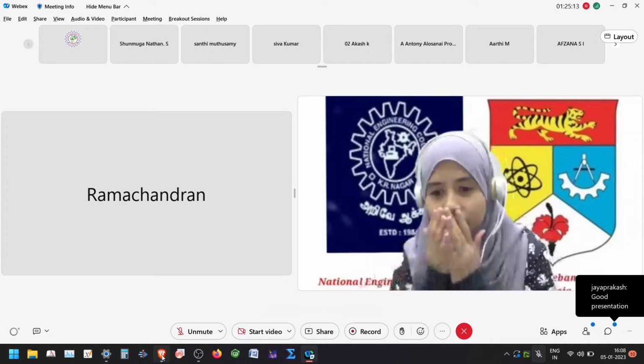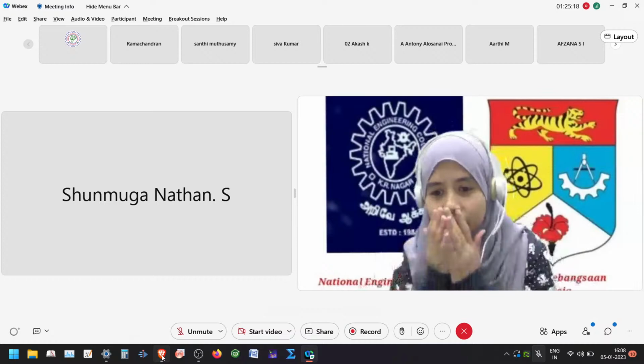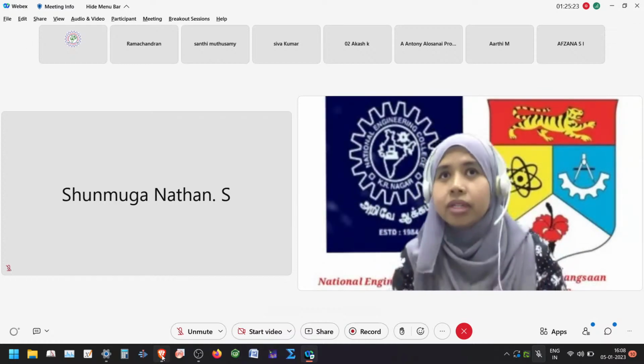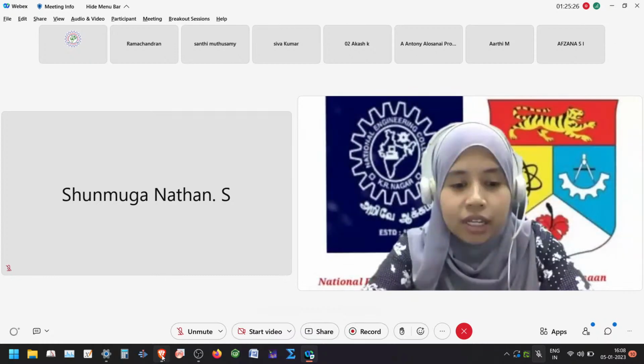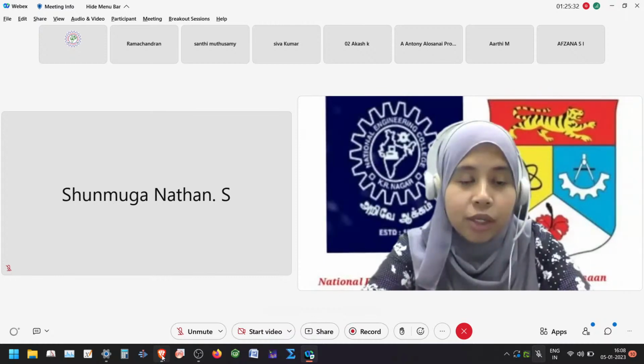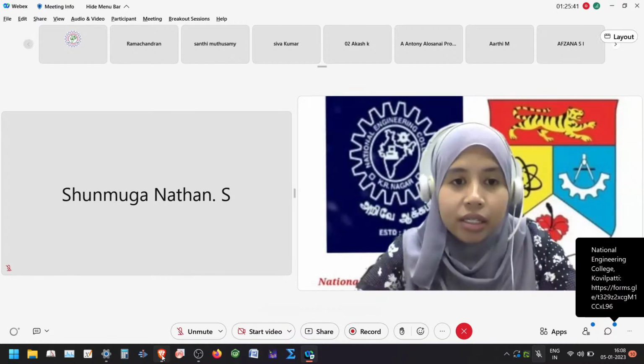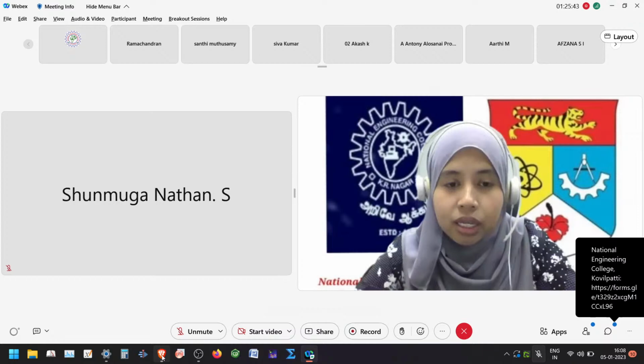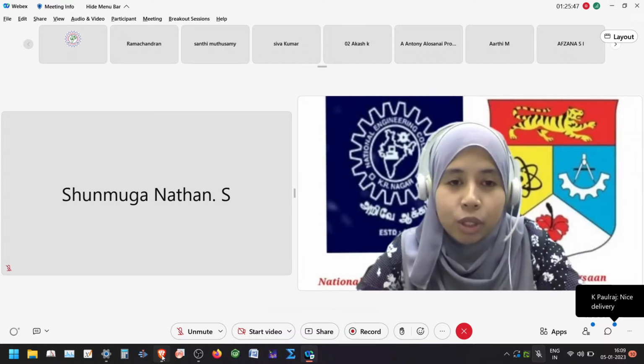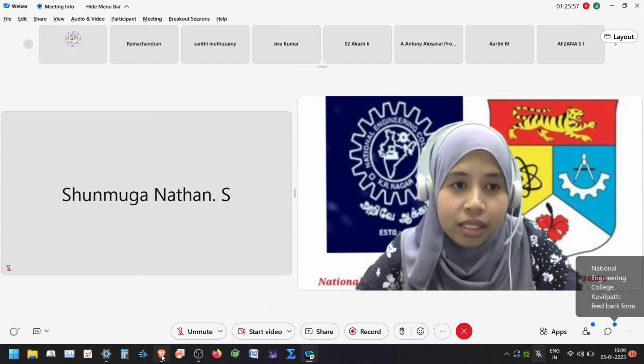Ma'am, you said that the Gongadze-Kornyshev model is applicable only at lower concentrations, right? Lower concentrations of electrolyte. Why is it so? This is because of the equation that they derived. When they use a higher current or higher concentration of the electrolyte ions, through the formulation, the diffusion is such that we tend to get very high specific capacity if we use higher current or higher concentration of electrolyte ions. That is actually not true for the interaction of electrolyte and electrodes, because it is impossible for us to get infinite capacitance if we use a higher concentration of electrolyte.